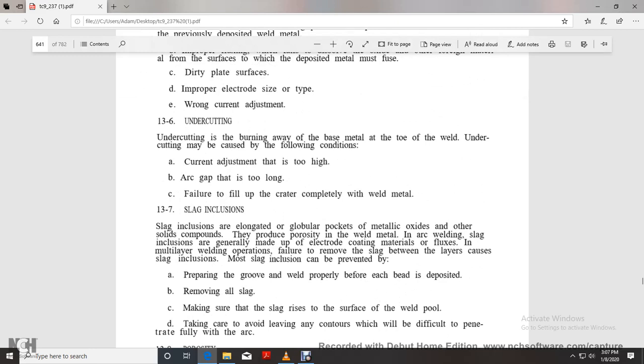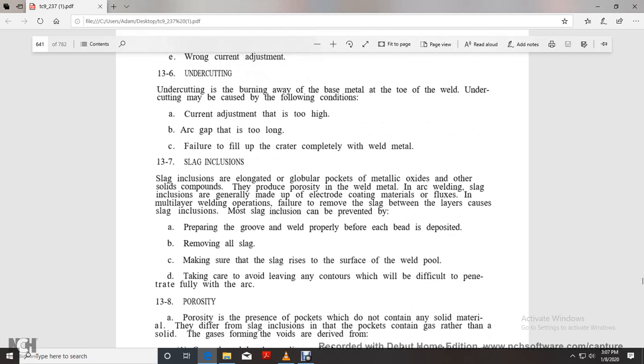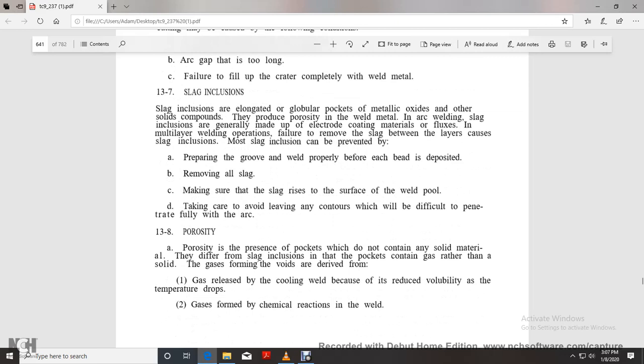Slag inclusion is an elongated or globular pocket of metal oxide or solid compound that produces porosity in the weld metal in arc welding. Slag inclusion is generally made from electrode coating material or flux in multi-layer welding operations. Failure to remove the slag between the layers causes slag inclusion. Most slag inclusion can be prevented by improving the groove of the weld joint before each bead is deposited. Remove all the slag, making sure all the slag rises from the surface of the weld pool, taking care to avoid leaving any contours that are difficult for the arc to penetrate fully.